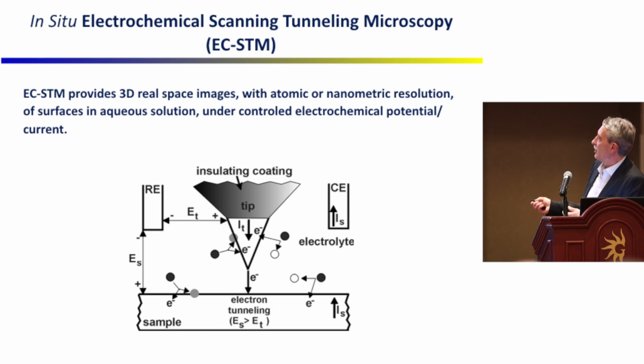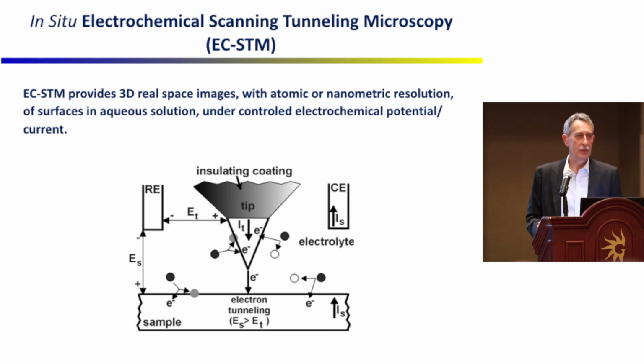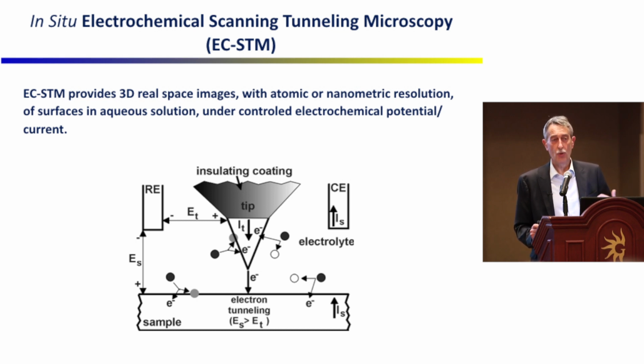because if you insulate most of the tip and just keep the end of the tip uncovered, then you can simultaneously record the tunneling current between the surface and the tip. And if you have two electrodes, you can record simultaneously the current potential curve. So you can do electrochemistry under controlled potential and current conditions, and at the same time image the surface with atomic resolution. And contrary to other techniques like scanning electron microscopy, what we get is a 3D image of the surface. And we get it in real space, in contrast with what you would get by doing X-ray diffraction.